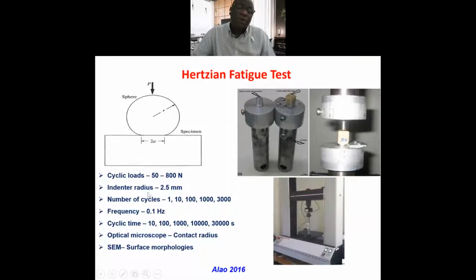The cyclic load fluctuates from 50 Newton to 800 Newton. The number of cycles: 1, 10, 100, 1000, 3000. So we use high load, low cycle. That one we mimic grinding of food. That is called bruising. Then the frequency applied was this, and this one leads to cyclic time of this. So we also use optical microscope and then SEM for surface morphologies.